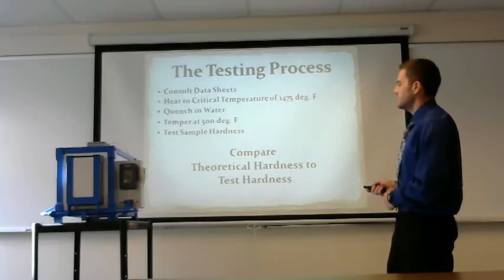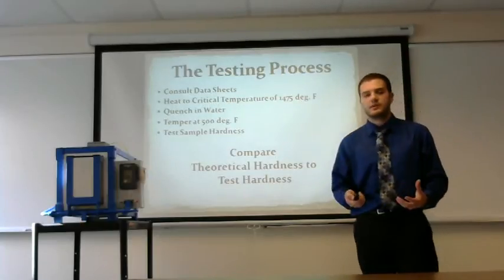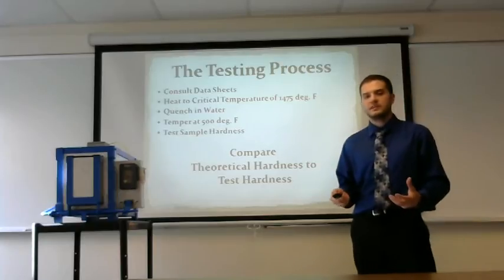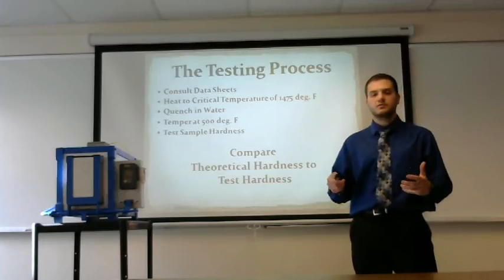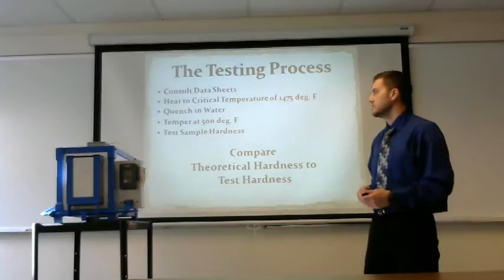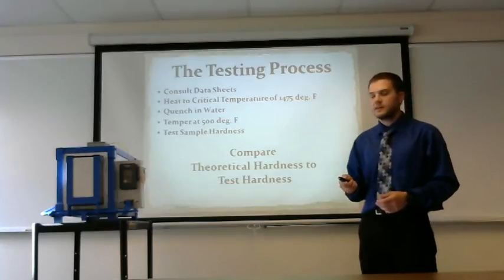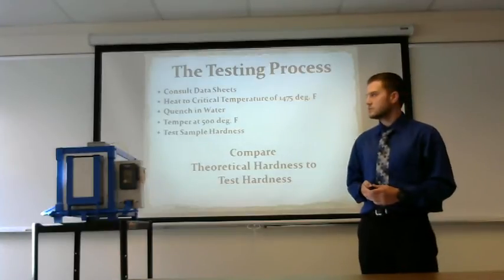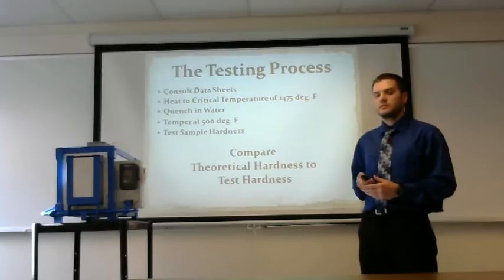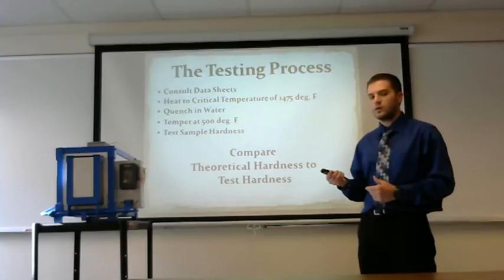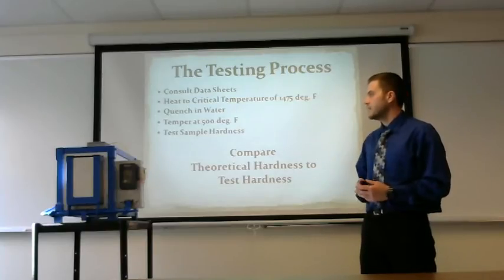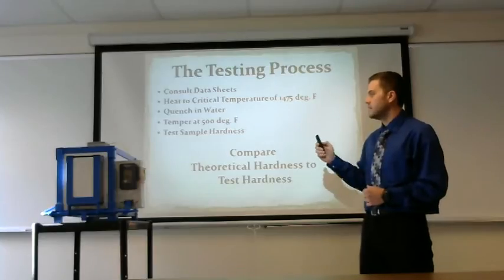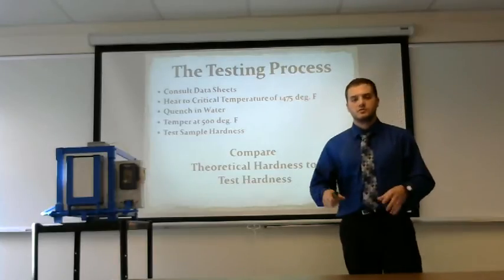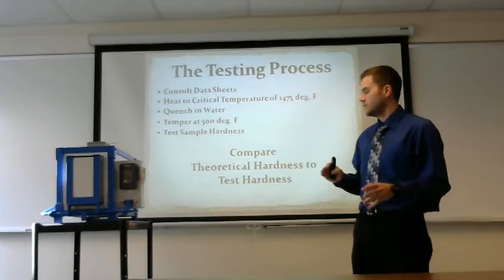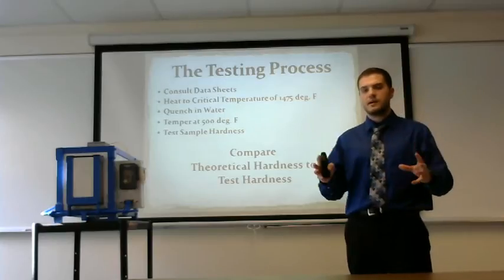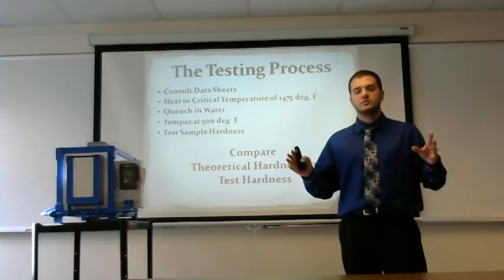Considering this a heat treat oven, I felt the best way to demonstrate it would be to heat treat an actual piece of steel. The process included reviewing data sheets, heating to a critical temperature of 1475 degrees, quenching in water, tempering at 500 degrees, and testing the sample hardness. The purpose of this will be to compare the hardness of the material to its toughness.